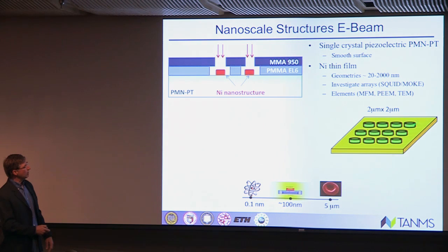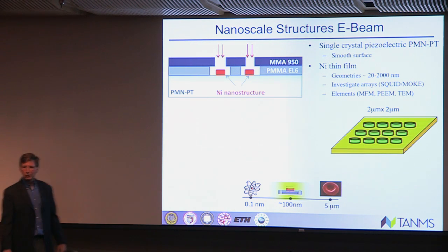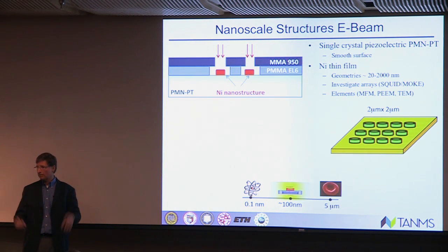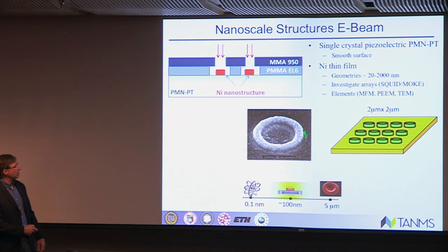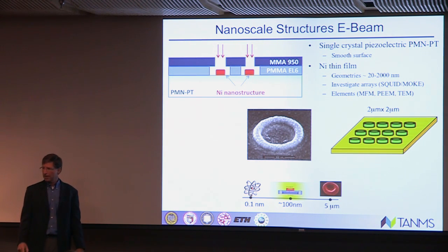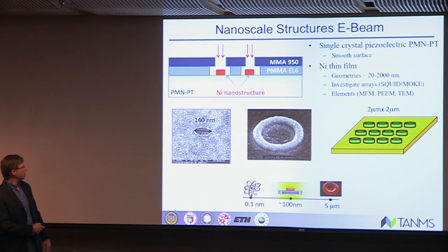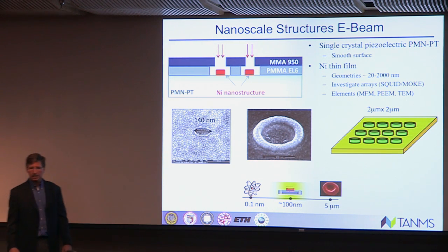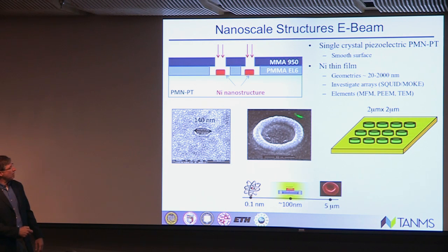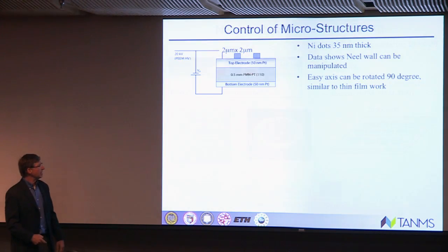So today we're going to look at some shapes about 2 microns by 2 microns. Now, that's not real small. Then we're going to go down and look at a ring structure. This is about 300 nanometers if you can't see it. So we're getting smaller. And then we're going to go down to something about 100 nanometers in size. Now, I'm going to plant a seed. If you look at this, this may look like a motor to you. And over here, this should look like a bit of memory to you. So now let's go through and see what we can do.